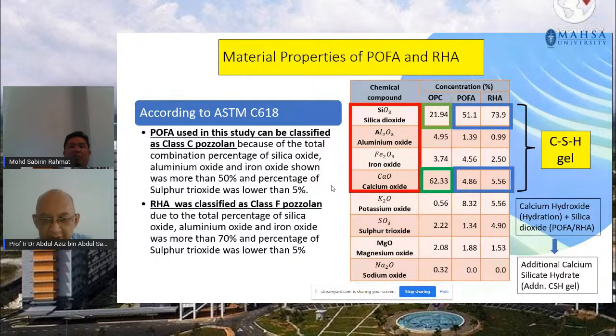But essentially, these 2 materials are the main actors in the cement, where when you add water, H2O, to these materials, they will combine, they will react and form into a gel. So by adding POFA and RHA, you have extra silica dioxide, which will react with the calcium oxide, and we suspect that this is where the extra strength of the green concrete comes in, when you have that extra silica dioxide coming into play with the calcium oxide.